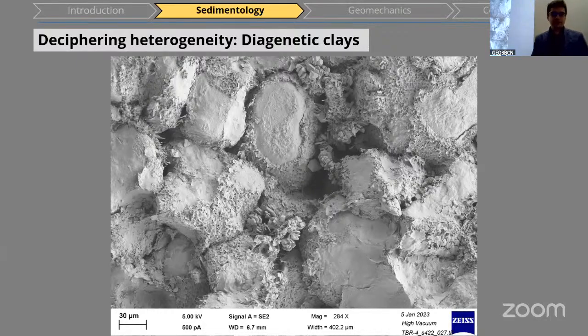So you can see here in SEM images these grains, and you can see these clay cutans, which really surround the whole grains. Here on top, there is none, probably because of the way this was prepared. But you can also see clays which actually fill the spaces between grains. So you can see here these nice clay platelets, and similar down here as well. So there are different types of clays, but predominantly, as we expected, there are a lot of these cutans around the individual grains.